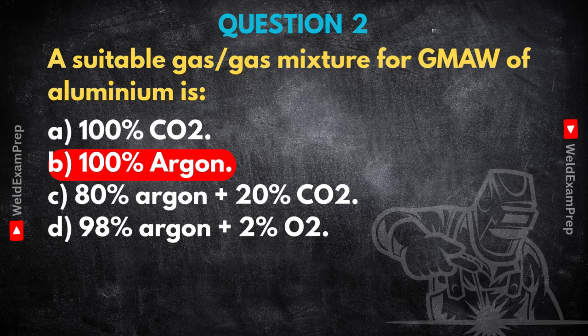Pure argon. What's really fascinating here and fundamental is the link between the material, in this case, highly reactive aluminium, and the shielding gas you need. Aluminium forms that tough oxide layer almost instantly in air. For GMAW, you absolutely must have a shielding gas that is totally inert. Meaning it doesn't react. Exactly. It doesn't react chemically with the molten metal or the hot surrounding area. Argon is a noble gas. It's perfectly inert for this job. It gives you a stable arc, helps ensure good weld quality, and critically, it prevents those harmful oxides forming in the weld.